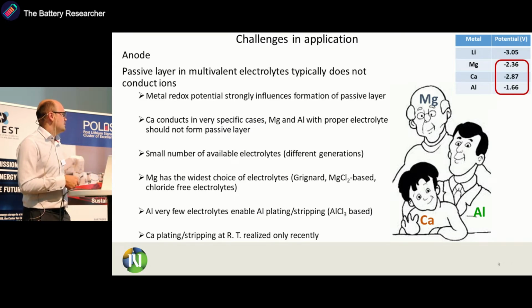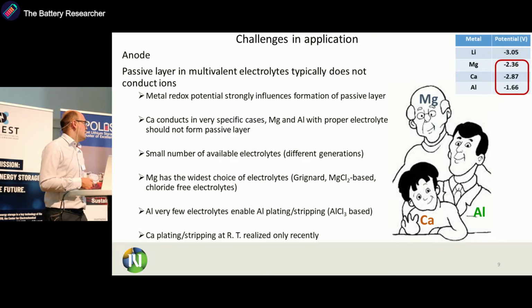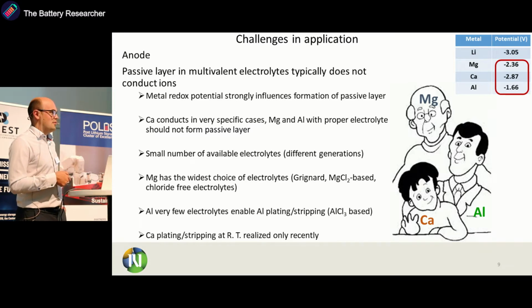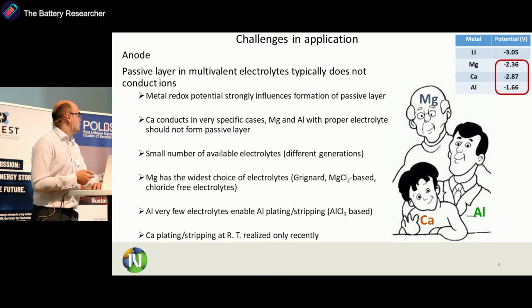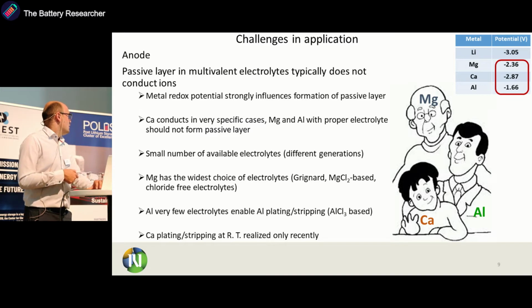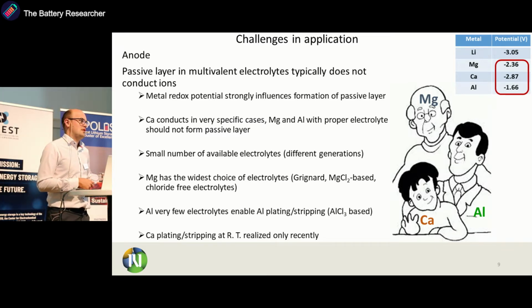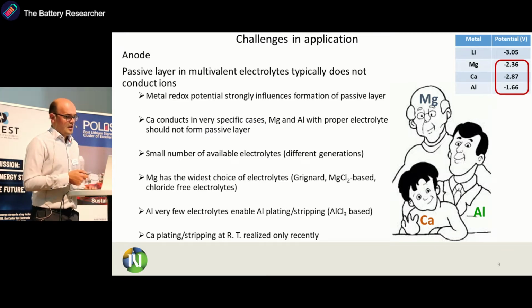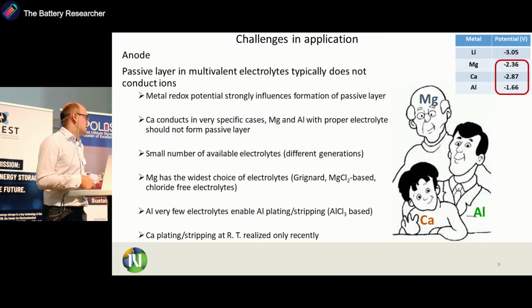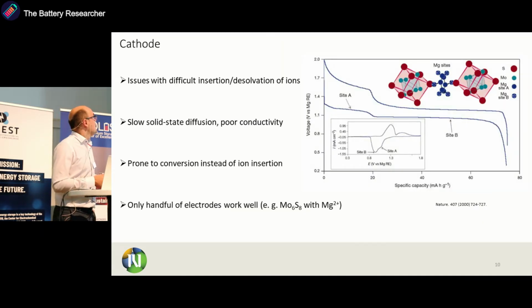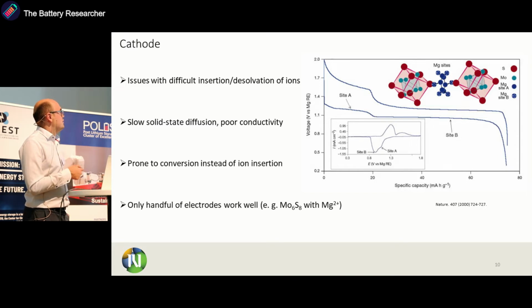We have Grignard-based, we have magnesium chloride-based, and very recently also chloride-free electrolytes. These chloride-free were pioneered by Toyota and also here by the group at KIT. With aluminum, we have very few electrolytes which enable reversible plating and stripping, and all of them are aluminum chloride-based, so it means we have corrosion issues. And with calcium plating and stripping, we have seen today that it was realized only recently, in 2019, at room temperature. On the cathode side, it's quite difficult to insert and desolvate ions.